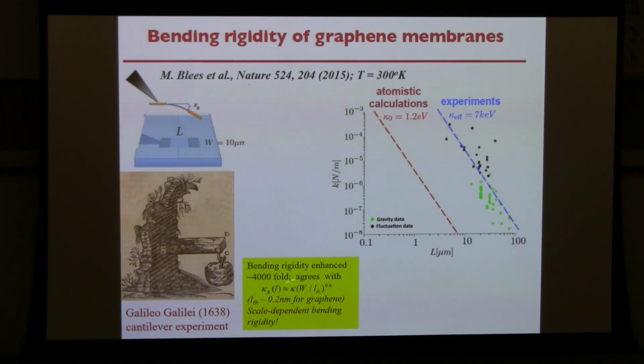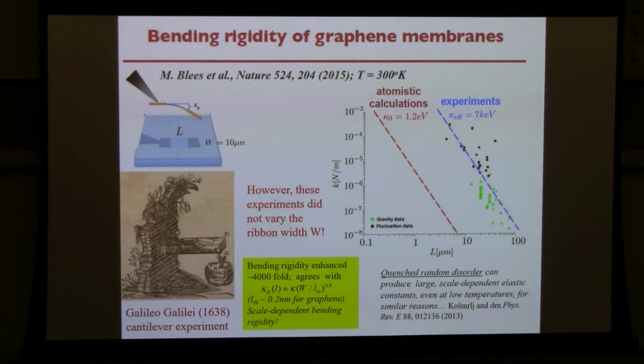This is what's expected as a function of the width of this ribbon. This is the scale-dependent elastic constant. But unfortunately, they never varied the width. They just measured it for a particular 10-micron width and said, whoa, that's big. And it's consistent with this theory that I've been telling you about.